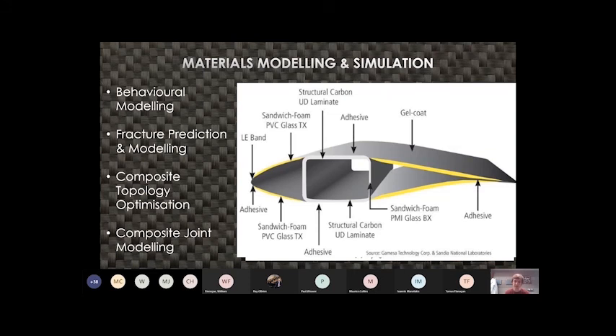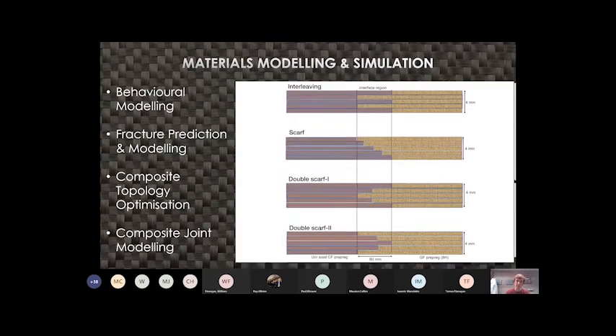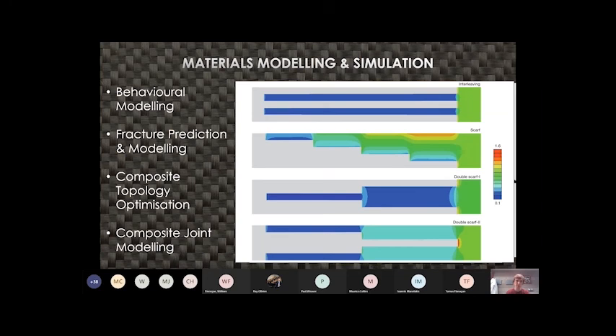So here, for example, we have a wind turbine blade. You can see the inner carbon spar and then the glass fiber outer shell. Essentially the point where these two meet is adhesively bonded in a lot of cases, unless it's co-cured. We've been able to test various different laminate types and joint configurations, and then by combining those with modeling tools, we can actually determine their behavior before we make the first prototypes, which saves a lot of money. Destructive testing is expensive, particularly when you're looking at carbon fiber materials.